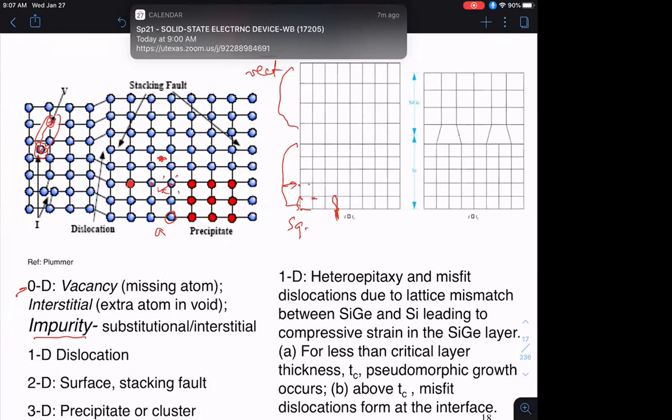Now, I also want to point out that when you hear the term impurity defect or defect, you get a knee-jerk reaction that, gosh, defects are definitely bad, right? Now, many defects are, right? But in the case of impurities, which are the donors or acceptors, those are intentionally engineered defects to change the electrical conductivity of the semiconductor. So, sometimes defects are purposely put in to get the functionality that you want. So these are examples of zero-dimensional or point defects, and they're very, very common.